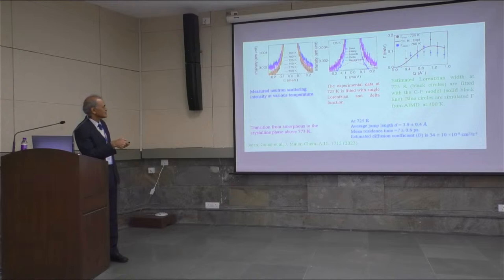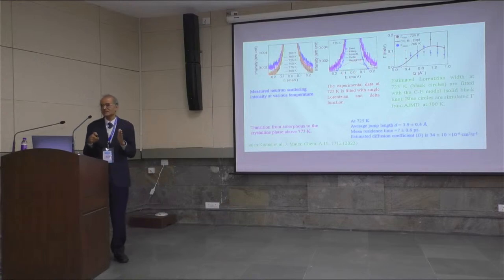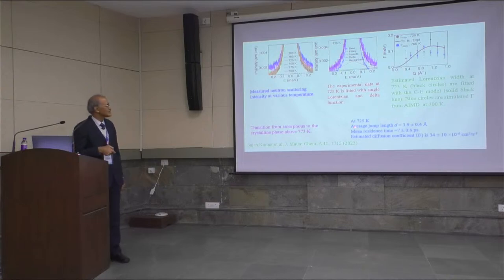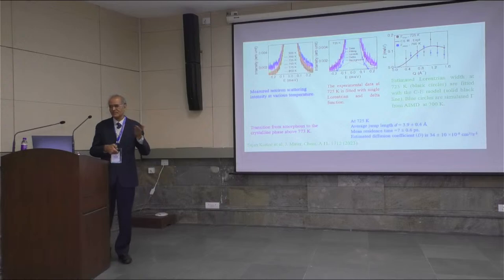So what this essentially tells us is that you can identify that there is diffusion. You still cannot identify which atom is involved, because purely experiment will not tell you that. For that there can be other experimental methods, but what we have done is through simulations. And then you can find out, for example, the average jump length of the lithium atom, which is typically 4 angstrom, related to some kind of inter-site distance. And there's a typical jump time of a few picoseconds, and there will be a certain diffusion coefficient.